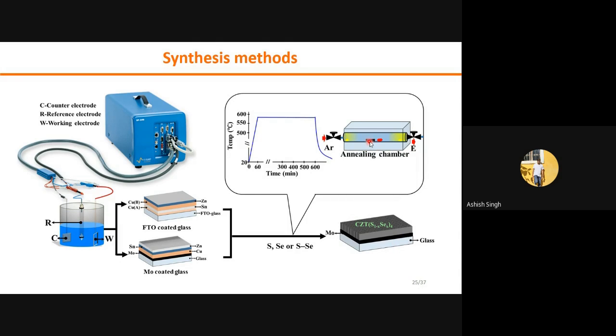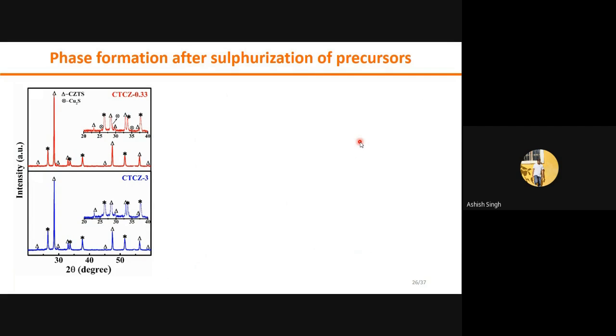So this is our sample. We put it with the sulfur and selenium, and we started annealing it at high temperature to make a compound semiconductor out of it. First we are going to discuss the phase formation after sulfurization of the precursor. In this condition, we deposited copper, zinc, tin on FTO coated glass and sulfurized it at 550 degrees Celsius for 2 hours to make the compound semiconductor.